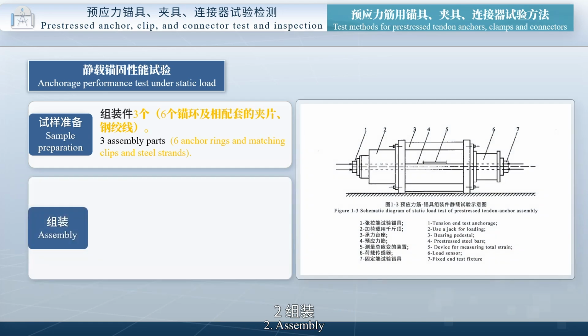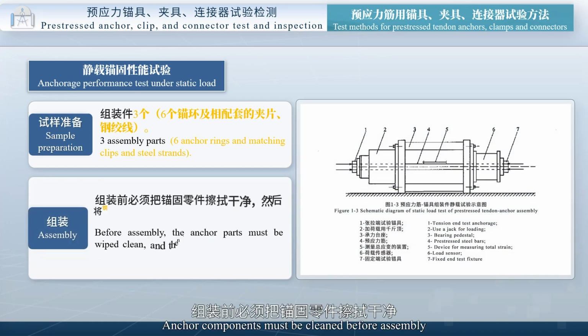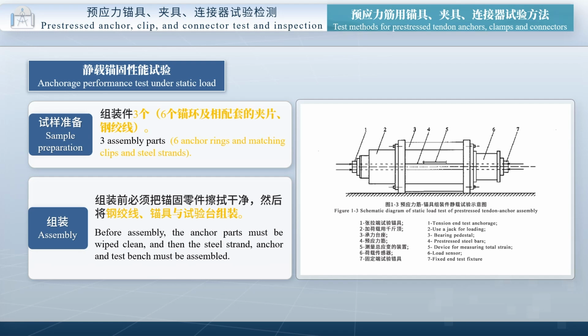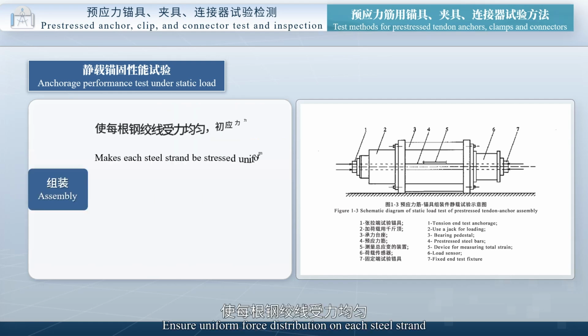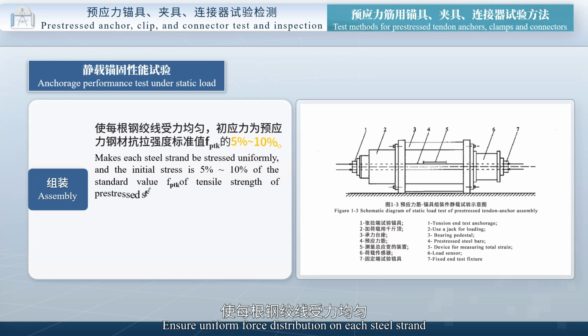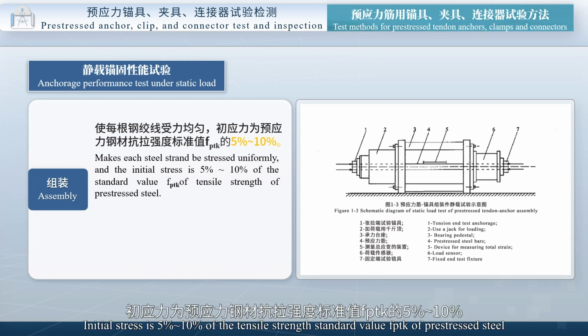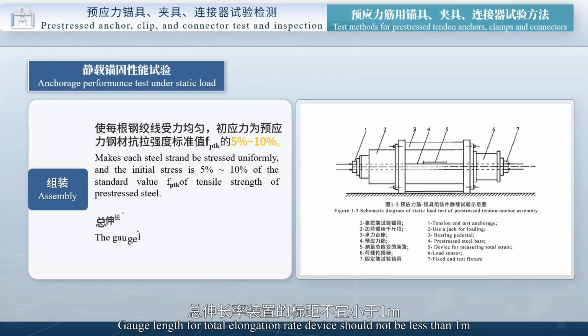Second, assembly. Anchor components must be cleaned before assembly. Then assemble the steel strand, anchor, and test bench, as shown in figure 1-3. Ensure uniform force distribution on each steel strand. Initial stress is 5% to 10% of the tensile strength standard value fptk of pre-stressed steel. The gauge length for the total elongation rate device should not be less than 1 meter.